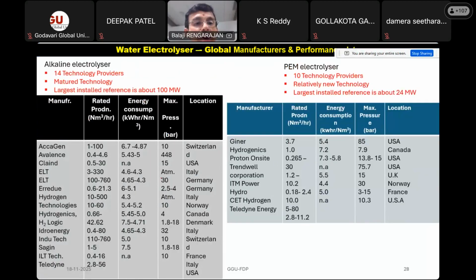And if you see the performance in all the cases, in terms of energy consumption per meter cube of hydrogen, it's close to 5 to 6 kilowatt hour per meter cube, or 5 to 7 kilowatt hour per kg. So if you want to produce 1 kg of hydrogen from water, the practical electrical energy consumption is close to 50 to 55 kilowatt hour per kg. Theoretically it requires 33 to 35 kilowatt hour per kg, but in the practical case it can be obtained only at the rate of 50 to 55 units of electricity per kg of hydrogen. That's what this entire table is showing, irrespective of the OEM and irrespective of the technology.